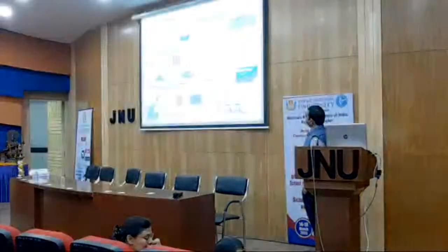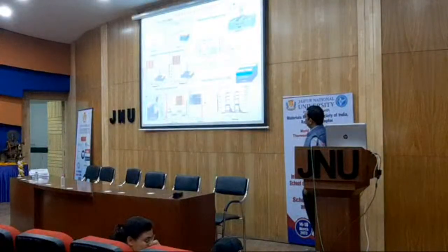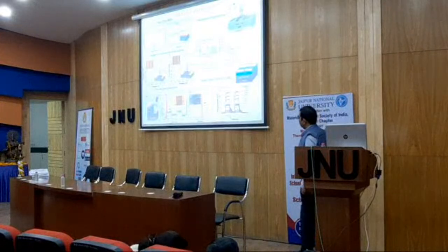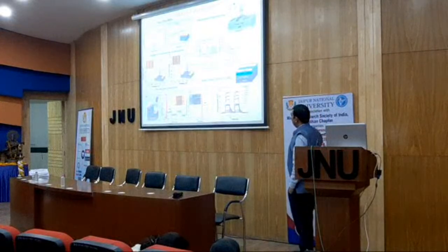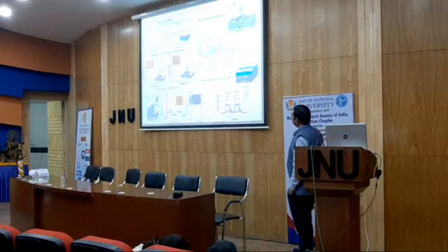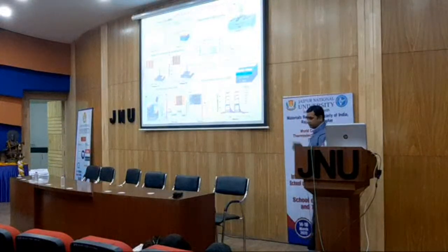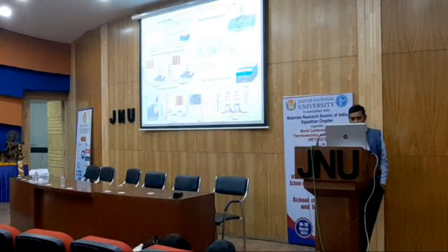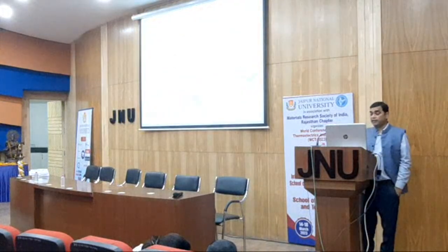The most important one was this one, which we published in 2017, and it became one of the highly cited papers in Applied Physics Letters, where this non-polar gallium nitride, which was grown on R-plane sapphire substrate, showed the highest responsivity which we have observed, of 340 milliampere per watt. At that point of time. Now we have moved up too much.